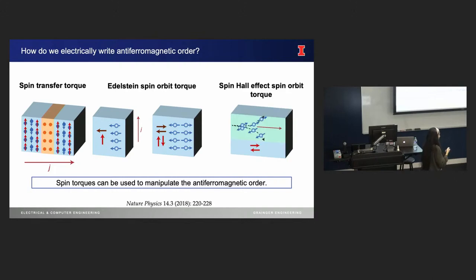So that's been done. And finally, the nice effect that seems to work is the spin Hall effect, spin orbit torque. You pass a current through this green layer on the top. I'm not sure if it's visible as a green layer from the back, but I have this green layer. You pass a current that exerts a spin torque on this bottom antiferromagnet and flips its magnetization. Now, the third effect seems to work very well whether your magnetic material is an insulator or a metal. We want to talk about how to utilize that in the case of metals. So, pop quiz time: what are the two methods that we will use to describe Mn3Sn for reading and writing? I'll remind everyone, for reading, we're going to be doing the anomalous Hall effect. For writing, we're going to be doing that last one.